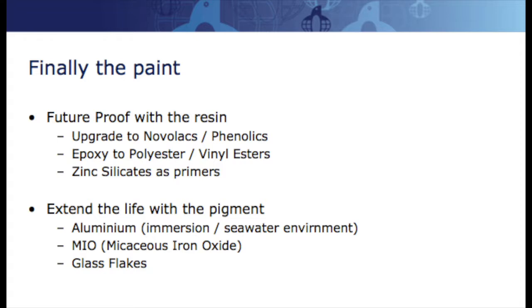So aluminium has been a mainstay for an awful lot of paint companies as a good anti-corrosive additional pigment. But it's only giving you an advantage in the situation of immersion or close to the seawater, close to water, because you're using it as a barrier. And it seems to give some other additional benefits as a pigment when you use it as the first coat, but it doesn't seem to give very much as the second coat. So it has its benefits, but be warned, because aluminium is quite sensitive to pH, high or low pH, and therefore will start to break down in the wrong environments.